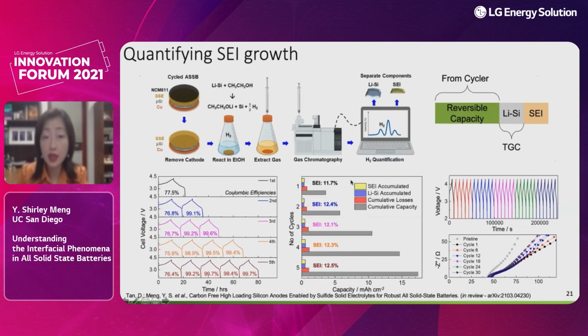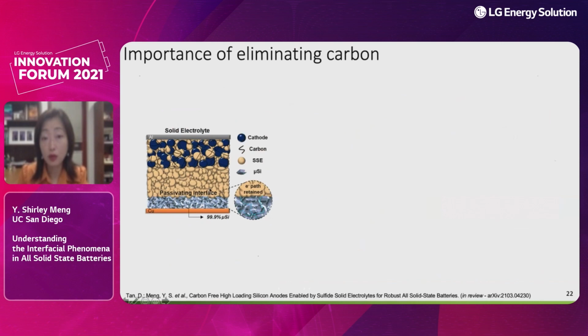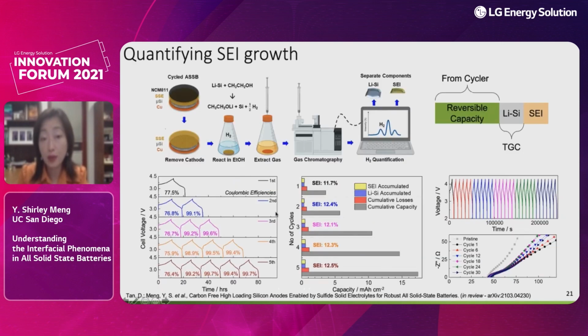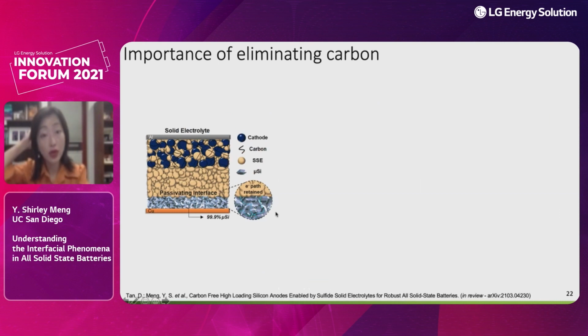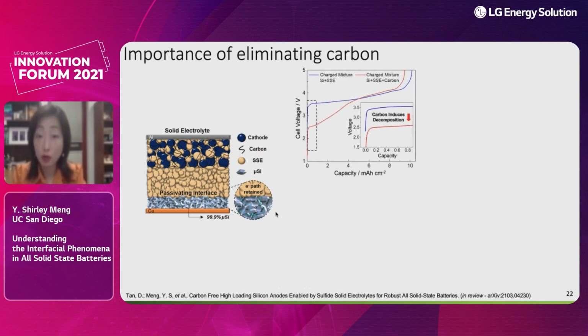The important aspect that Darren, my student, was very courageous to try, is to think about the narrow electrochemical window of the sulfide electrolyte, so he completely eliminated the carbon. As a controlled experiment, we wanted to show people what happens if you do have carbon in the anode. If you have carbon in the sulfide electrolyte, the carbon will facilitate side reactions.